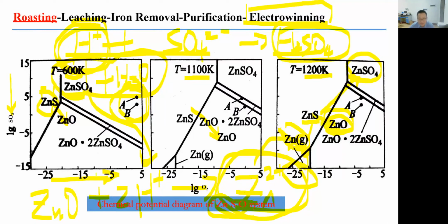And the sulfur in this process, when we are producing zinc oxide, will move to the gas phase, and it will transfer into sulfur dioxide. And with mature chemical technologies, sulfur dioxide can be easily transferred to sulfur trioxide. And when we are absorbing sulfur trioxide with water or with dilute sulfuric acid, we can produce this very important commercial product, sulfuric acid.